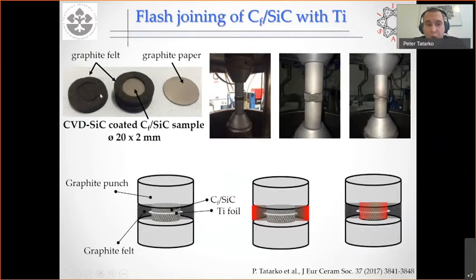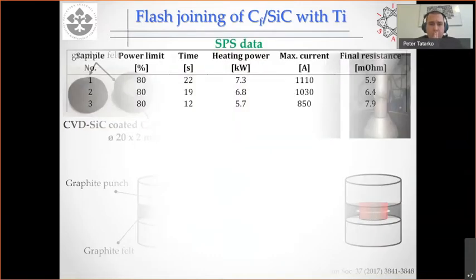So why did we use this felt? We were relying on the fact that at the beginning of the process, graphite felt has lower resistance than our samples. So the graphite felt will actually heat up first, then it preheats our sample, and then the resistance of the sample drops, and then of course the current goes through the sample and we can obtain the joint. That was our hypothesis, that was the idea, and I would like to now show you how we explored it.